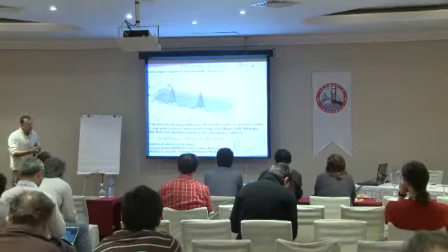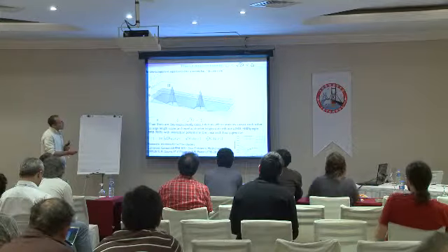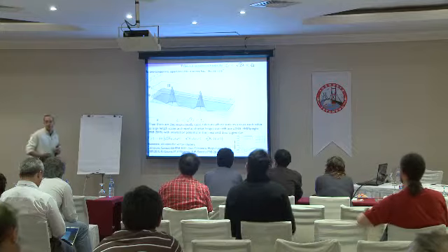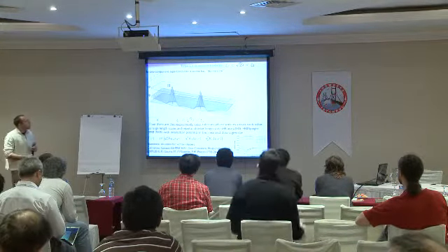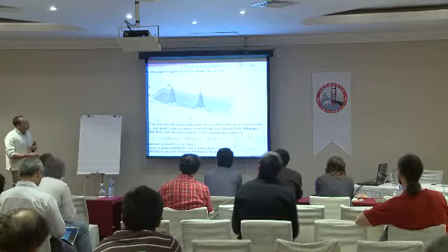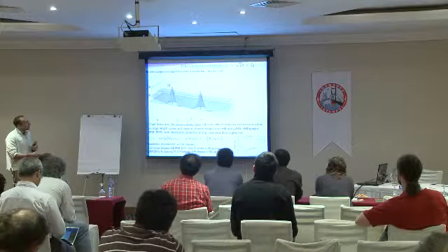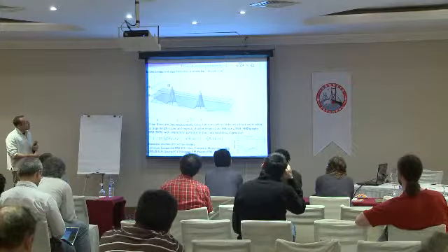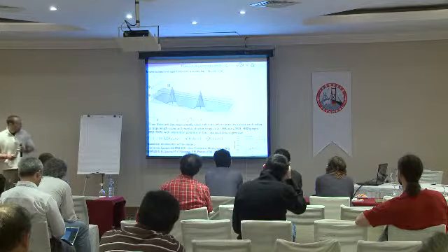So then the vortices. If you have two different coherence lengths, there is nothing fundamental which can prohibit this type 1.5 region, with one Ginzburg-Landau penetration depth running in between two coherence lengths. And then your vortex will have two cores. If these are very different, then one core will be very large, this is the core of psi 2, this is the core of psi 1, very small, and the magnetic field falls somewhere in between.